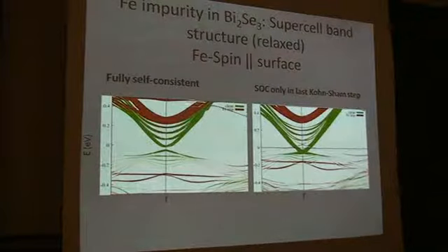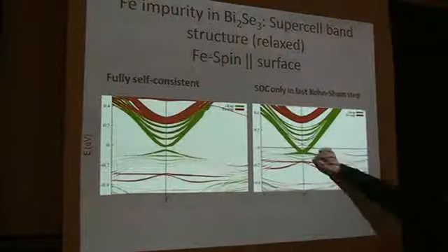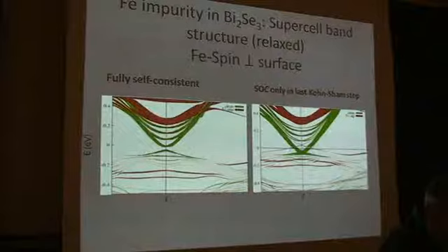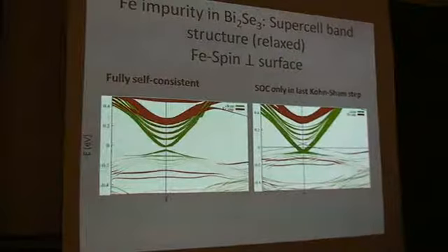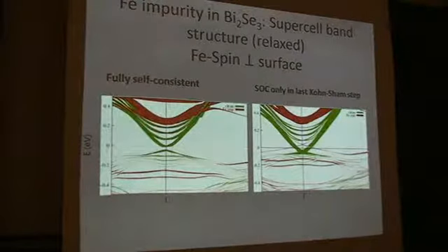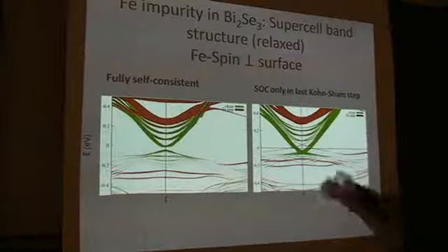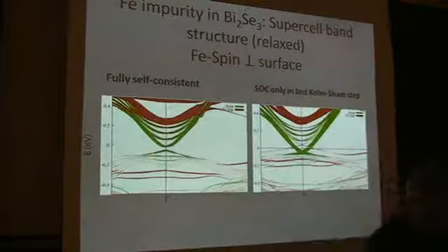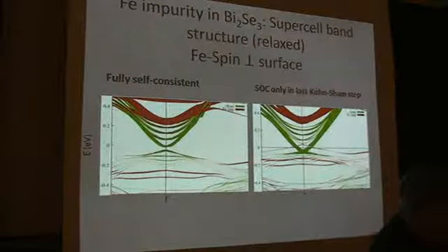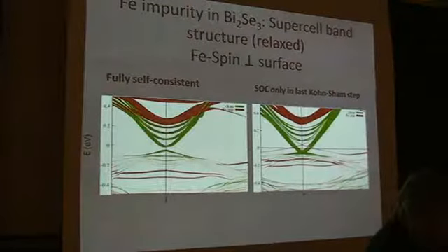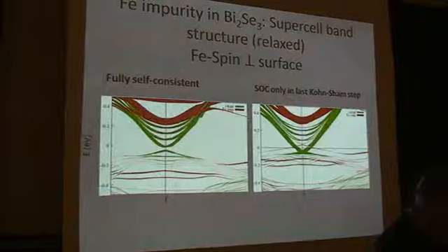But then what we can do is turn on spin-orbit coupling at the last stage, or we can do it fully self-consistently, and there is very little change. So as long as you ignore these kinds of modifications, there is no gap opening, there is no additional feature. What's more surprising is that, at least in this calculation, putting spins out of the plane doesn't change the result either. Whatever the density of states, whatever the band structure, we don't see any additional gap opening for the spins out of the plane. And so we will continue, and at some point we'll get to the bottom of what's really happening.